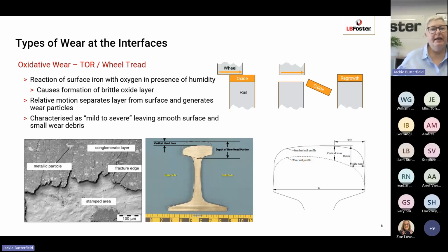So what happens here is it causes the formation of a brittle but very, very thin oxide layer on the surface of the steel. So as the wheel moves, this oxide layer sits on the top of the steel, and the force and the relative motion separates that oxide layer. So it skims it off the top of the rail. The oxide layer is removed as wear particles and debris, and then the cycle will begin again and you'll get regrowth of that oxide layer. So this is a constant process of oxide formation, removal, and regeneration.